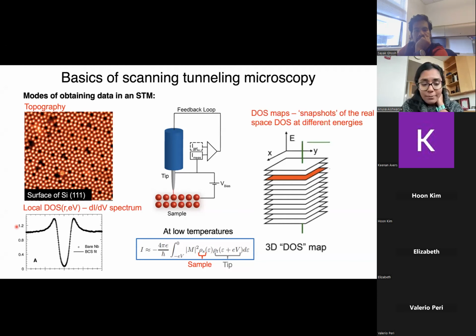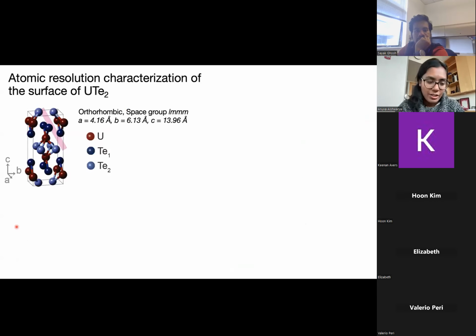We can also do something else, which is take spectra at different positions in real space and then map it out as a function of energy. This gives us a three-dimensional data set where at each energy we have a snapshot of the real space. And if we translate that into Fourier space, we can get information about quasiparticle interference, band structure, and so on. So coming back to UTe2,